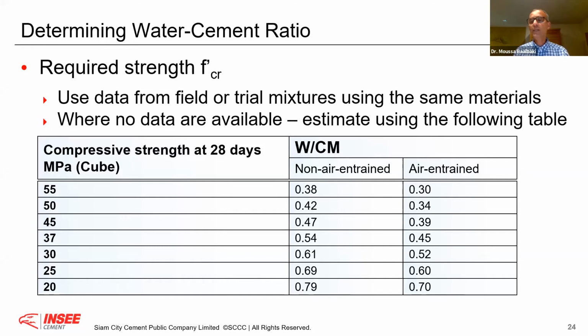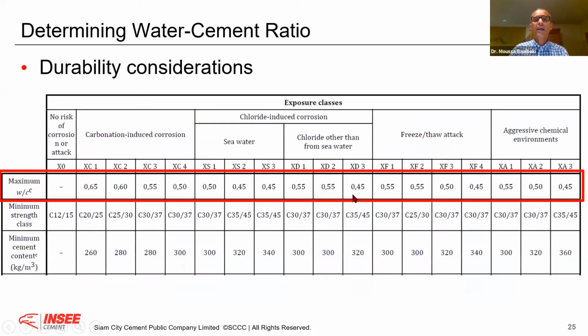Because corrosion will take place within the 20 years if your concrete is exposed. Okay, you should keep this in mind. This is really important. Now, you see, exposure condition, if I take XS1, 0.5. I cannot go above 0.5.